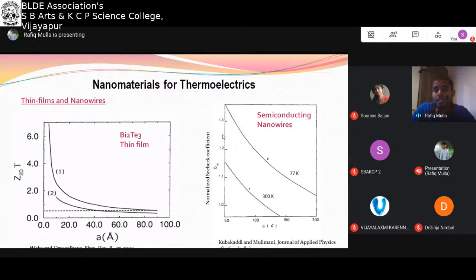Similarly, the Seebeck coefficient improvement has been predicted theoretically when the dimension of nanowires is decreased. You can see at 200 angstrom thickness, means around 20 nanometer thickness of the nanowires.